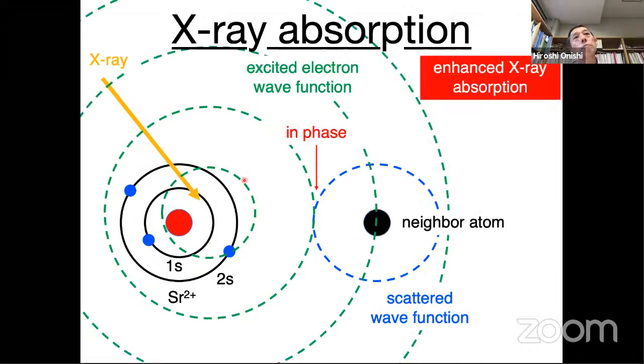Then this spherical wave is expanding in space, and there is a neighboring atom in the photocatalyst crystal, perhaps an oxygen atom, an oxygen anion. Then the expanding green wave function is scattered by the neighboring atom. As a result, the spherical wave, represented by the blue circle, is a scattered wave propagating from the neighboring atom center in this way.